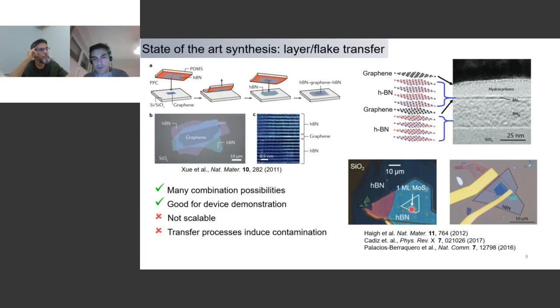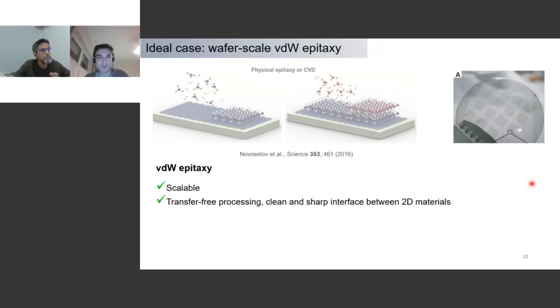Here is just another example. You have hBN combined with molybdenum disulfide, where you can also see this kind of contamination that's trapped at the interface. And here another example where you combine a single layer graphene with TMD and boron nitride. So very sophisticated structure, but it's a small area, and you may suffer from contamination. And again, you may even process this into a device like shown here with contacts, but at the end of the day, you have one single device. You don't have millions of devices as you want to have in any technological application integration.